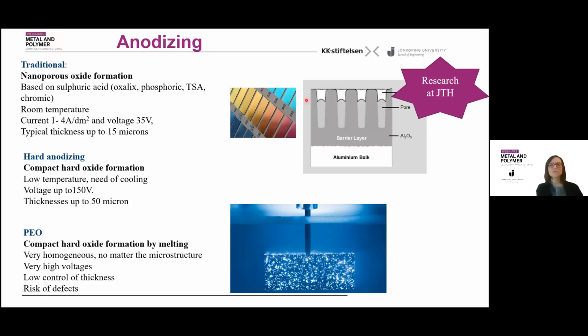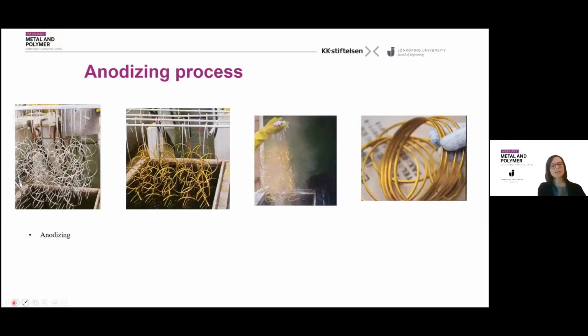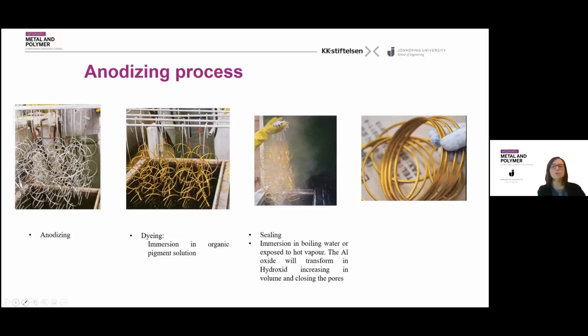At the very end, you should close these pigments by a sealing treatment. You start the anodizing by applying an external current to the aluminum component, then immerse it in a dye pigment containing bath to give the final color. Then you close this porosity by a water or vapor treatment that transforms the top layer of the oxide into the hydroxide, increasing the volume and closing the porosity, ending up with a very nice colored oxide surface layer.